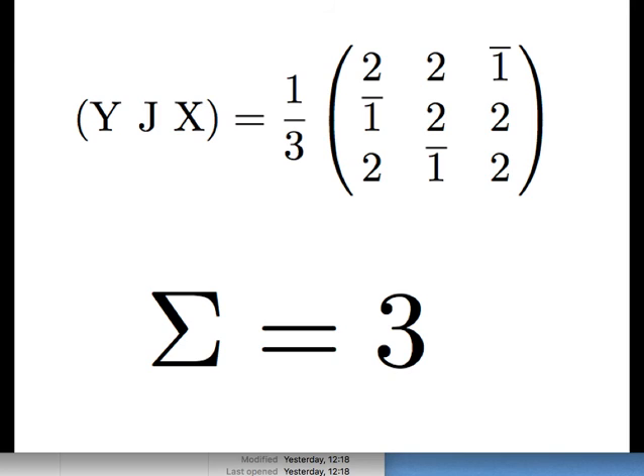And when we introduce texture into the material by particular kinds of deformation, the probability of getting coincidence site lattices increases, because the crystals rotate in a way that will minimize the interfacial energy. So if you introduce low sigma values, then you are actually reducing the total interfacial energy per unit area, even though the total amount of interface may not be decreasing. You are introducing more low energy interfaces than high energy.